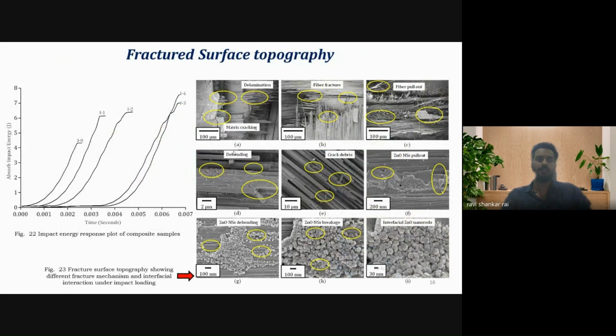After that, this is the failure graph of the absorbed impact energy. So what has been done: as the nanostructure development inside the system increases, the time taken to failure also increases. It was like a brittle fracture, but still there was some time to allocate it. And we have also achieved a high absorbed impact energy.